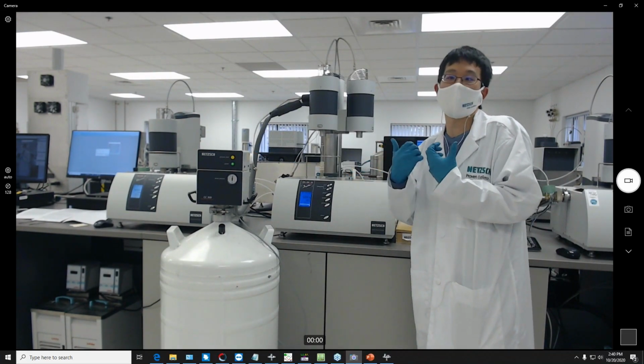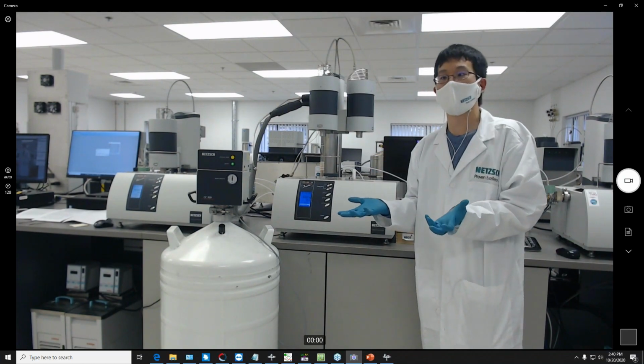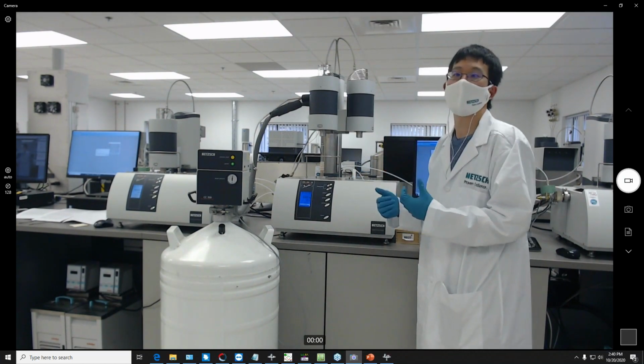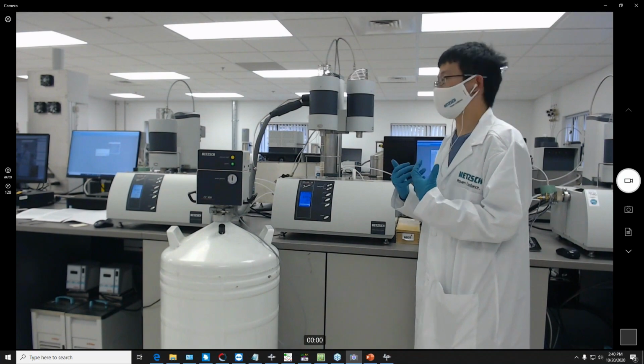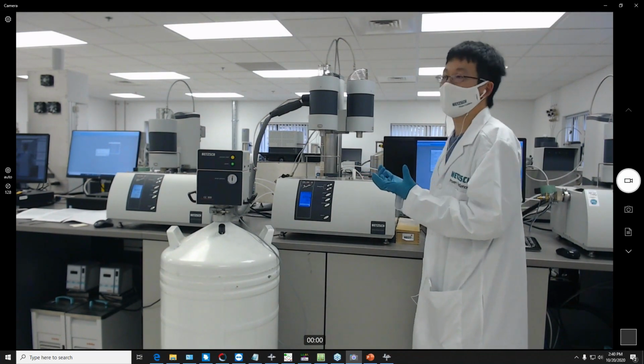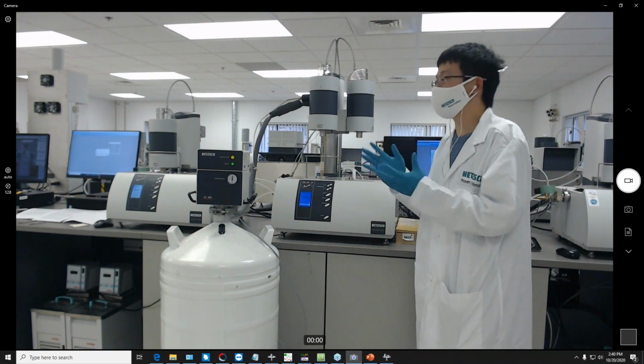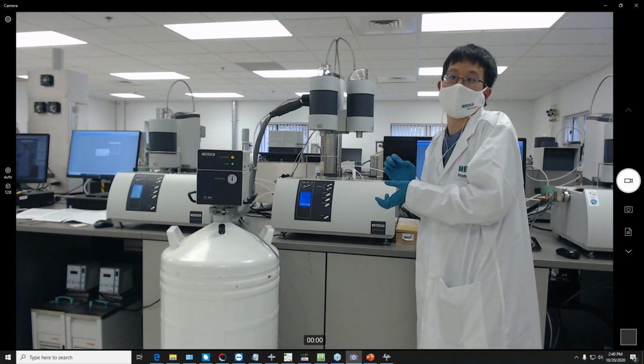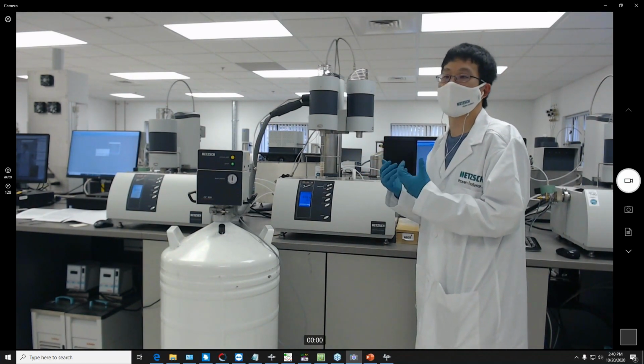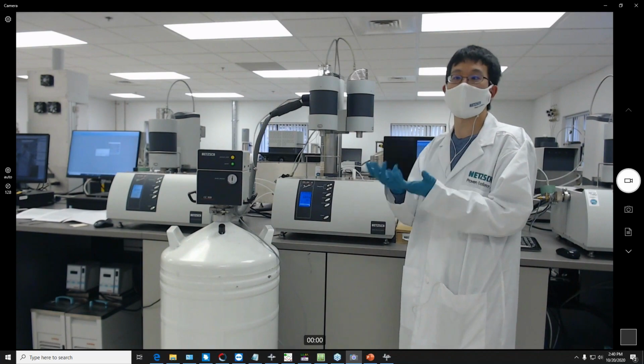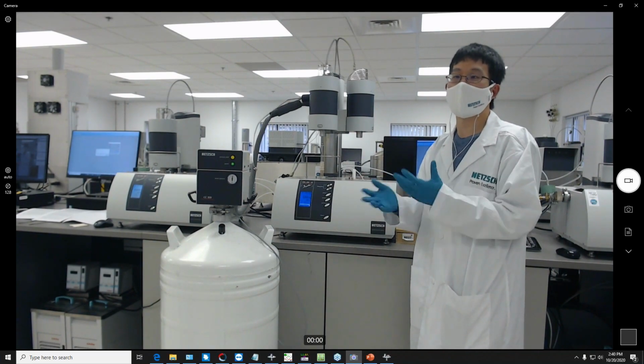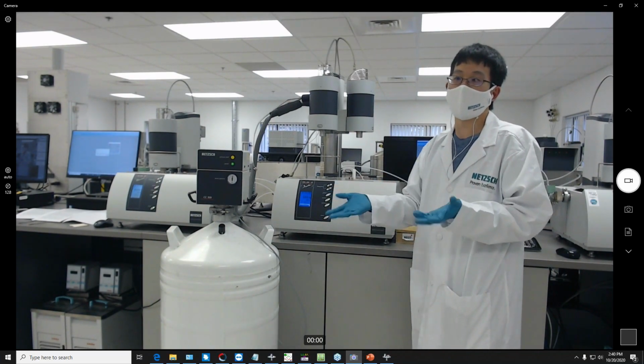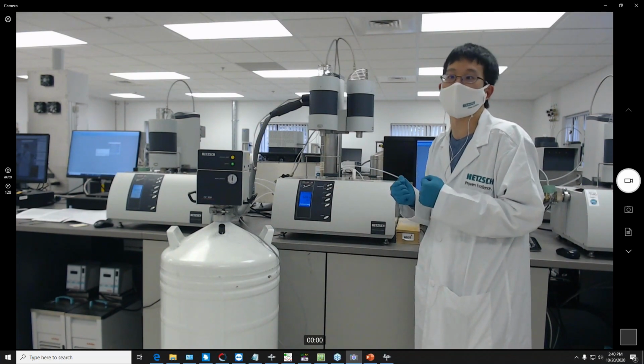That's why we always recommend you perform a correction measurement with 2 empty crucibles. This will collect the inherent baseline values of how your setup is behaving. And then when you perform a correction plus sample measurement, it will subtract out these signals so that you will generate the signals of just the sample.